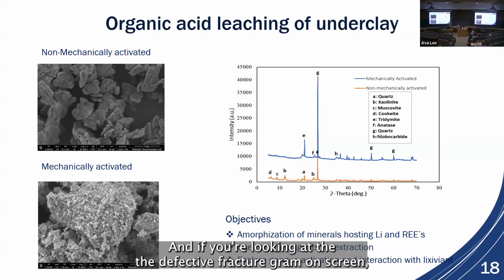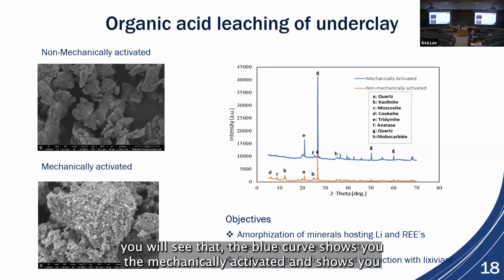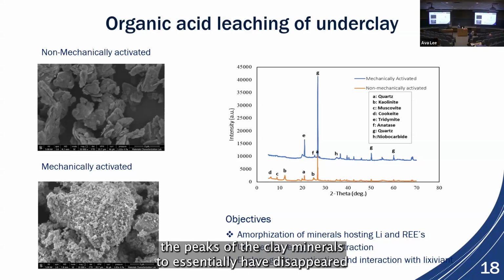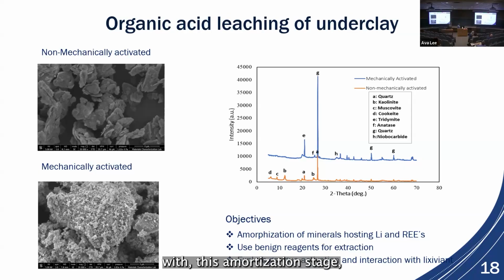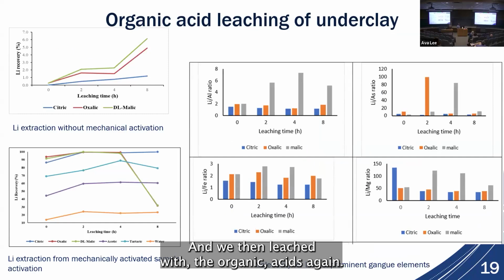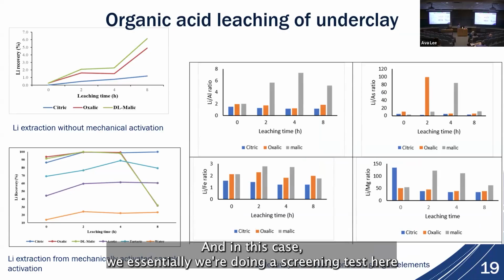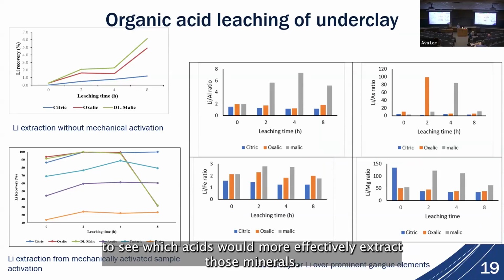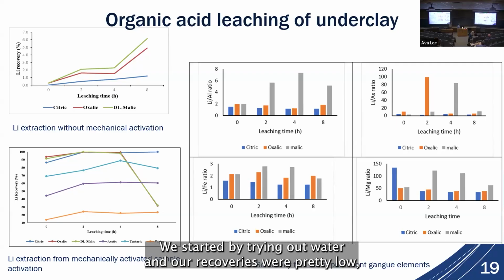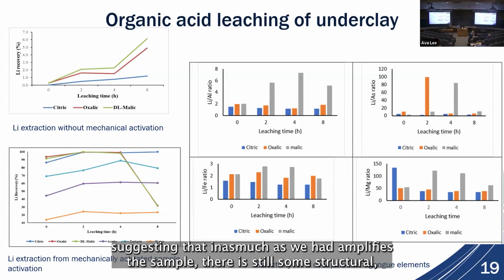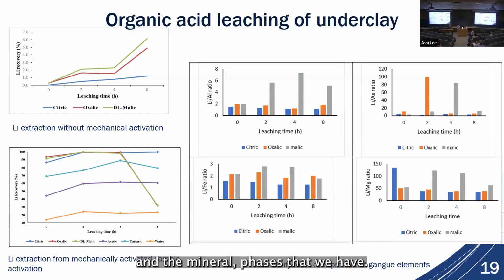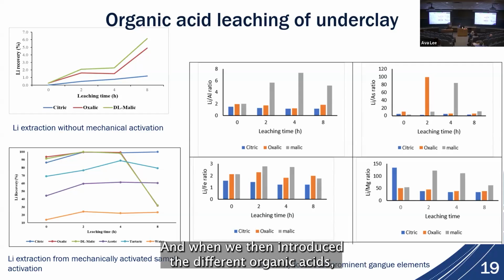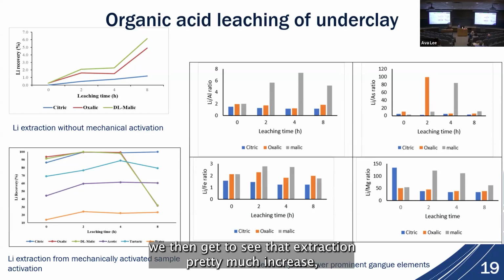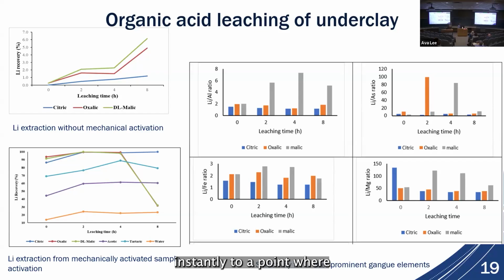And if you're looking at the diffractogram on screen, you will see that the blue curve shows you the mechanically activated and shows you the peaks of the clay minerals to essentially have disappeared with this amorphization stage, which then means you have altered the crystallinity of that material, and we then leach it with the organic acids again. And in this case, we essentially were doing a screening test here to see which acids would more effectively extract those minerals. We started by trying out water, and our recoveries were pretty low, suggesting that in as much as we had amorphized the sample, there is still some structural integration between the target element and the mineral phases that we have. And when we then introduce the different organic acids, we then get to see that extraction pretty much increase instantly to a point where kinetics are not an issue.